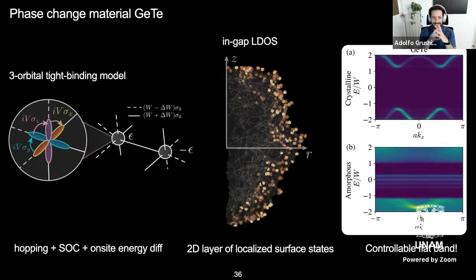If in a disordered system you don't have K, normally the states wouldn't have a well-defined momentum. However, imagine that your electron has a very long wavelength. Then it doesn't really care what type of lattice you have. So it's propagating essentially freely, and what that means is that it has a parabolic dispersion, which is what you see here. And the reason it's well defined is precisely because of the fixed coordination.